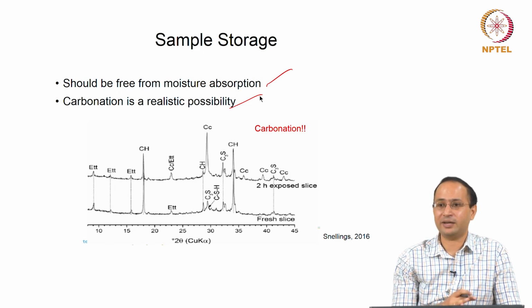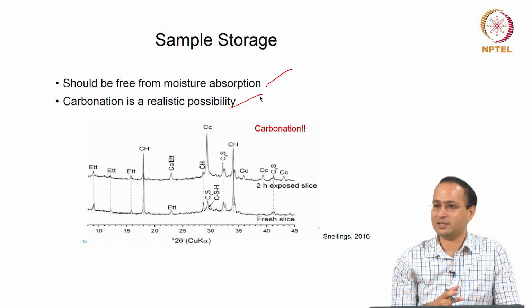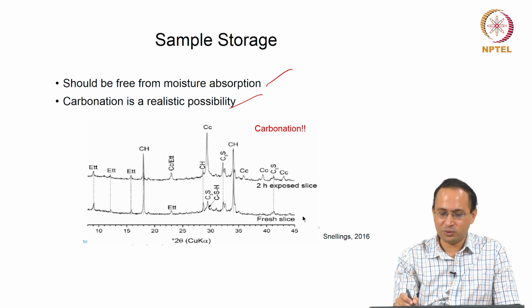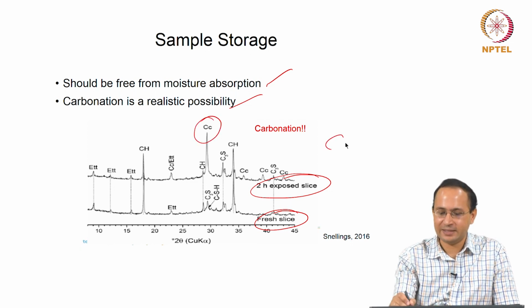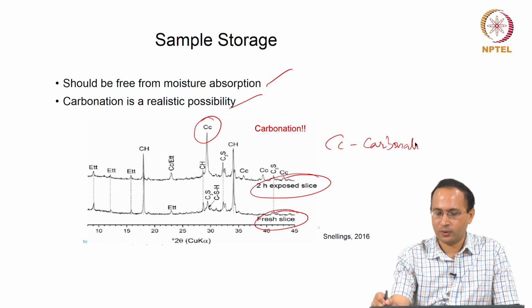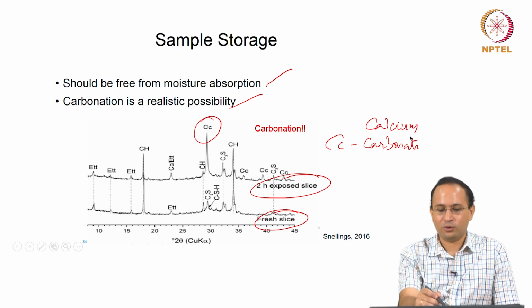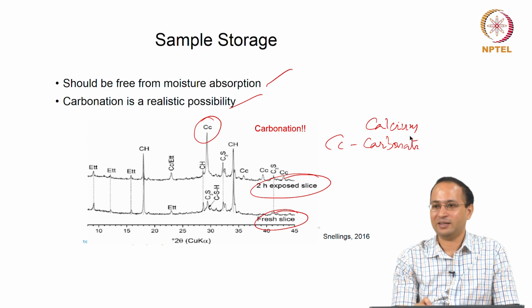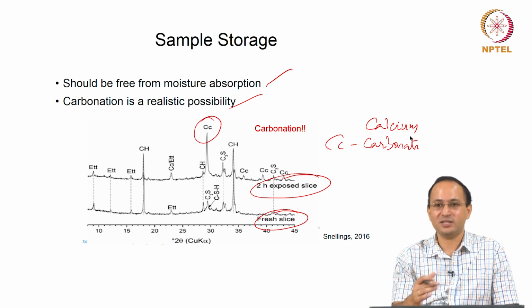You have calcium hydroxide in the system, and calcium hydroxide tends to carbonate, forming calcium carbonate. Also you have instances of carbonation of calcium silicate hydrate. In this case you see this is a fresh slice, this is a 2-hour exposed slice. What do you see? See the occurrence of this Cc, Cc is carbonate, okay, calcium carbonate. So, when you are exposing it to the atmosphere, you are seeing the formation of calcium carbonate. You do not want that, right, because that is altering your phase assemblage. So, these are the things you have to keep in mind.